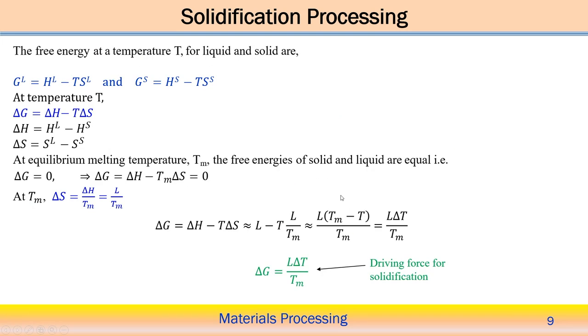So, here we see the free energy at temperature T for the liquid and the solid. GL gives the absolute value of the free energy. GL is the enthalpy minus T into SL, so we are assuming this at temperature T. Similarly, GS equals HS minus T SS, that means the Gibbs energy for the solid phase is HS minus T SS.